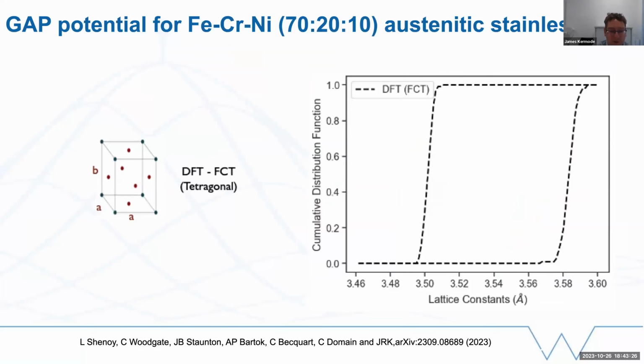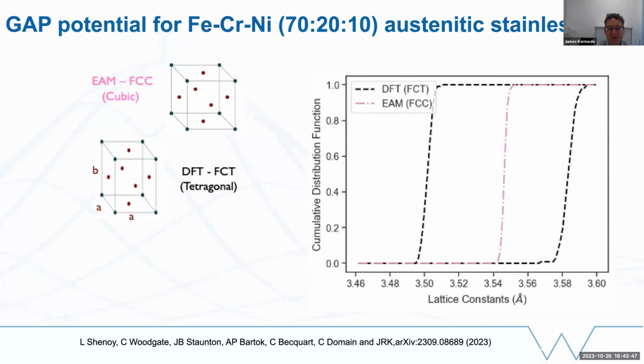So if we look first of all at what we get from DFT, it does describe this one long direction nicely. We have two shorter lattice constants and one longer lattice constant, and there's a distribution of values that you get because of the random ordering in the alloy, but you get clear separation of these things. If we use a simple embedded atom model, it doesn't know anything about spin. It can't really describe this at all, and so it gives you a cubic structure with just one lattice constant.